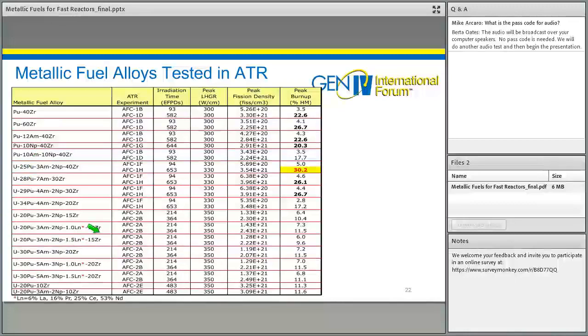But for critical systems, we've even tested a wide spectrum of metallic fuels, some with quite high contents of plutonium, which would be capable of driving down the conversion ratio of a reactor, maximizing minor actinide destruction. Some significant quantities of minor actinides. We've looked at tests with simulated rare earth or lanthanide carryover. And we've taken some of these fuels tests to very high burnups.